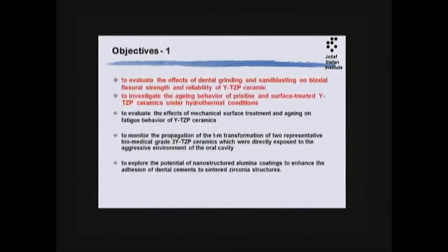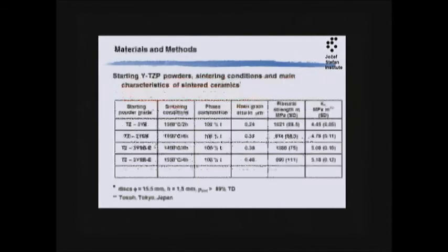So let's go first to the effects of the mechanical surface treatment and the effect of aging, and we'll go through the results. These were the very first results. The materials here are the standard grade. At that time, E stood for experimental grade, and now I have corrected the grain size values. We have measured the equivalent diameter, but now in the standard it says the intercept, you just cut the microstructure by a line, and that makes a difference.